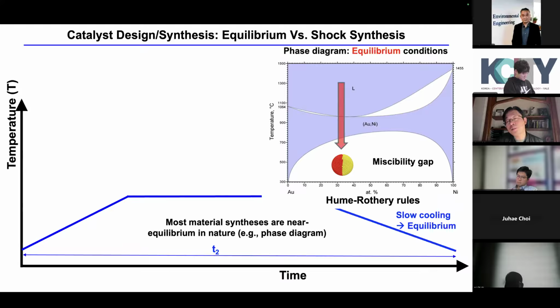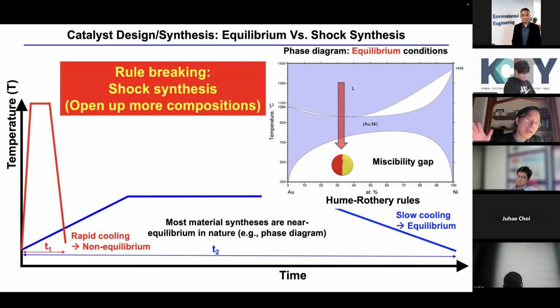You know that, for example, gold and nickel, you say, I cannot make it. No, don't do that. But a lot of catalysts require you to mix some elements that usually don't mix, for example cobalt and moly for ammonia chemistry. In that case, we have to find a way to mix them, right? So that means we have to break the rule. We cannot follow the thermodynamics. So in this case, we basically increase the temperature to a very high temperature.